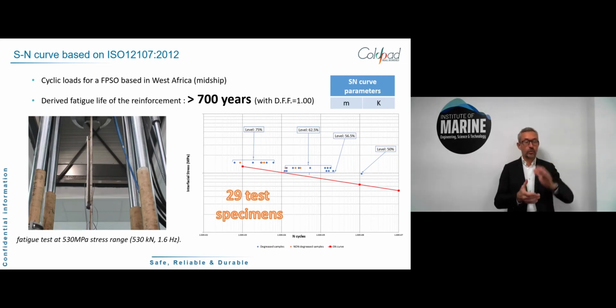All right. So what you can see here is that what we have developed with Bureau Veritas is the first SN curve for bonded composite reinforcements. We've used the ISO which is dedicated to SN curves. We made many samples, as many as were required, and then we were able to elaborate this SN curve. We applied this design to the midship of an FPSO, and we derived the design life in fatigue, and we arrived at 700 years of design life for a DFF, a design fatigue factor, of 1.